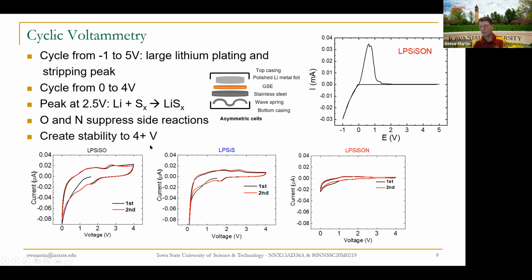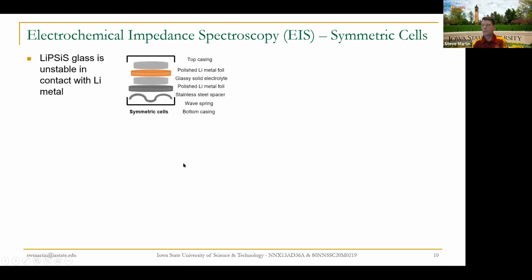So we get 4 volts. Why is 4 volts important? Well, that's the voltage that you operate cobalt oxide, nickel manganese cobalt oxide. That's the voltage of the lithium ion battery. So we need to be stable out to that 4 volts, and you can see these glasses do that very well. We do another thing called electrochemical impedance spectroscopy.